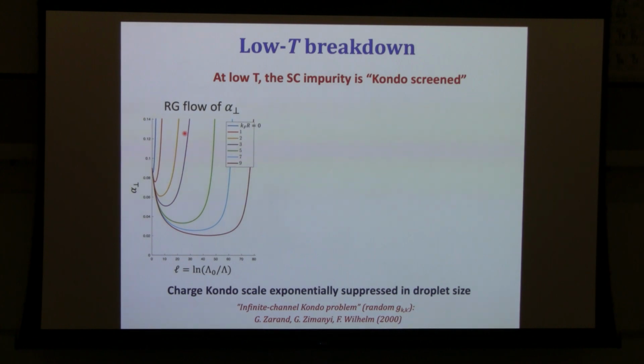Okay, and this is an RG calculation with some distribution of coupling constants with a varying number of channels. So this is what happens to the dimensionless coupling constant as a function of the running RG time. It begins by flowing down, undergoes a minimum, and eventually there's one channel that wins and takes it all, and just screens the impurity. So this is RG time, so there's an exponentially large energy window where this simple-minded picture that I showed before actually works. So this is the phase diagram that we would expect that we derive for this model.